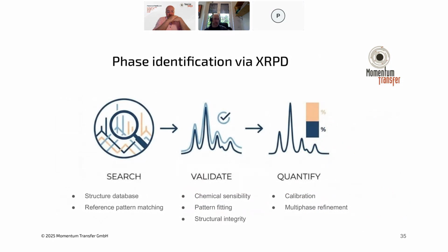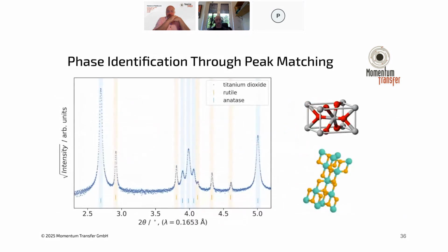So the main application that we see with mineral analysis is phase identification and quantification. In that sense, we can use these data to search for candidates of structure phases that are present in the material by reference pattern matching, which I showed in the beginning. We can use preliminary refinements to validate the presence of those phases, and then complement that, ideally, with chemical analysis or other information that can help to rule out cases where there might be similarities in candidates that can be difficult to distinguish. And then we can quantify all of those components as well.